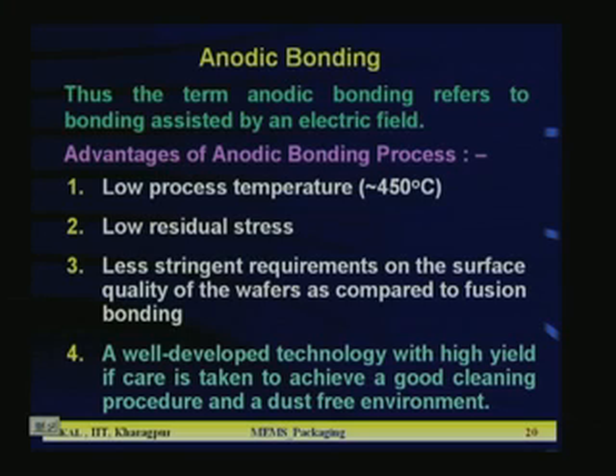Third one is less stringent requirements on the surface quality of the wafers as compared to fusion bonding. Fusion bonding, we told you, should be highly smooth, with smoothness less than 10 angstrom RMS value, but here that stringent condition is not required because you are applying high voltage. This is a well developed technology with a high yield if care is taken to achieve a good cleaning procedure and a dust free environment, but people look for a dust free and clean environment there.